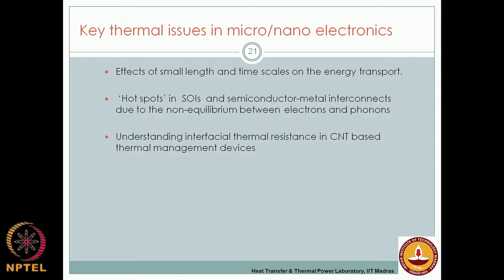Since we have wave-particle duality, you can always associate these lattice vibrational waves with a particle called phonons, and you can give them a certain energy and so on. The interaction between electrons and phonons is going to be at non-equilibrium all the time, and therefore results in the generation of these hotspots. So, what is important for better thermal management is to understand thermal interface resistance well, the generation of these hotspots, and how we mitigate them by means of efficient materials such as carbon nanotubes.